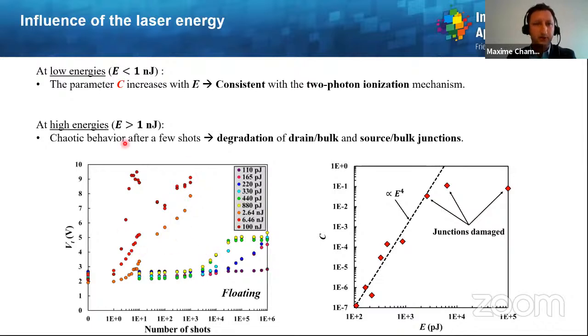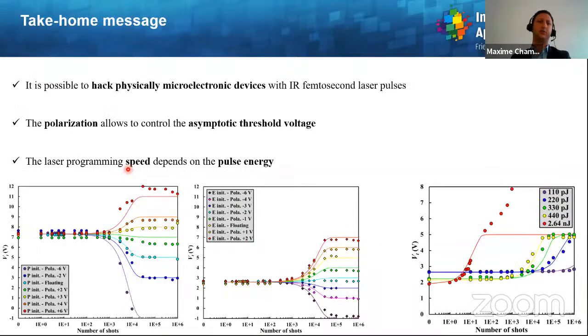One can also note that at high energies, there are some chaotic behaviors after a few shots, which are related to the degradation of the drain-bulk and source-bulk junctions. So here is the take-home message for this part. It is possible to hack physically microelectronic devices with infrared laser pulses. The polarization allows us to control the asymptotic threshold voltage, and the laser programming speed depends on the pulse energy.